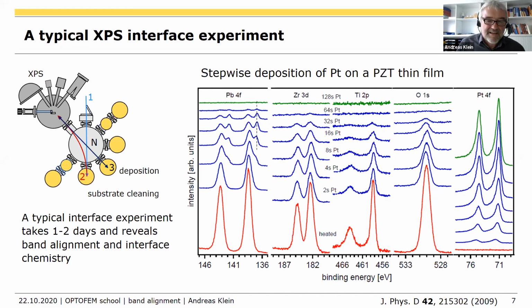There may be some materials, but I guess mostly transition metal oxides, where such a shoulder can be related to oxygen vacancies. My first argument always is that a vacancy cannot emit an electron. And what we see here are electrons emitted from oxygen atoms. And I take a shoulder which is emitted from an oxygen atom to say that there is an oxygen vacancy in the material. That's pretty strange.